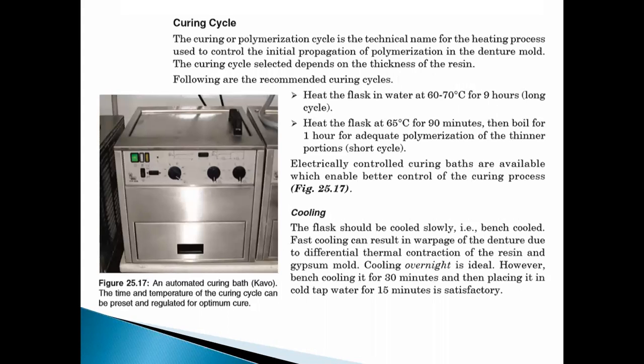So we'll do the final curing. Different manufacturers give different types of curing cycles according to their own manufactured products. The most common is that the flask is kept in water whose temperature is about 60 to 70 degrees Celsius for 9 hours. This is known as the long cycle. Another is the short cycle, where we keep the flask in water at 65 degrees Celsius for 90 minutes, then boil the water for an hour. Okay, to make sure that the thinner portions are also cured.